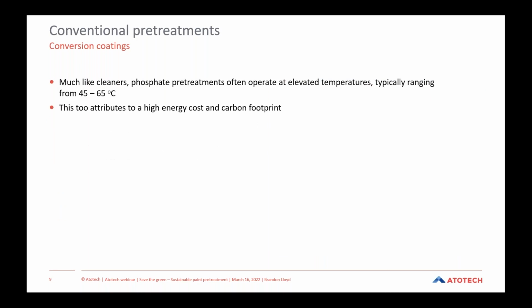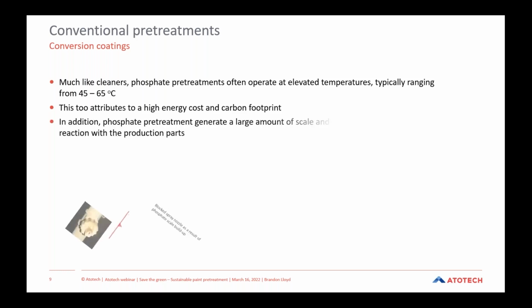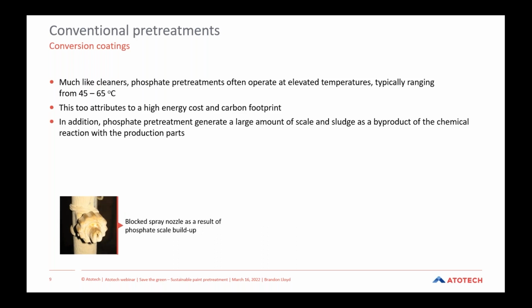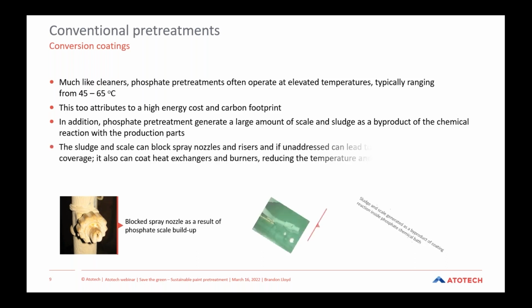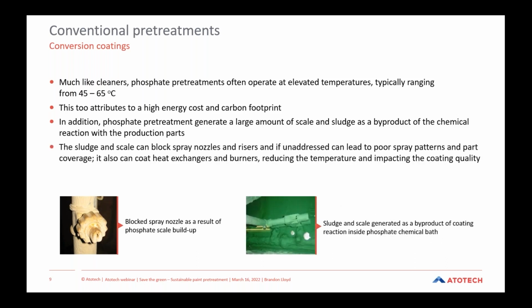Much like cleaners, phosphate pretreatments do often operate at elevated temperatures, and in the context of conversion coatings, typically we're discussing 45 to 65 degrees Celsius. And again, this too attributes to a high energy cost and associated carbon footprint. In addition, phosphate pretreatments can generate a large amount of scale and sludge as a byproduct of the chemical reaction with the production parts. This sludge and scale can block spray nozzles and risers, and if it's left unaddressed, can lead to poor spray patterns and part coverage. It can also coat heat exchangers and burners, which will ultimately reduce the heating capacity for the process itself, which can impact the final part quality.